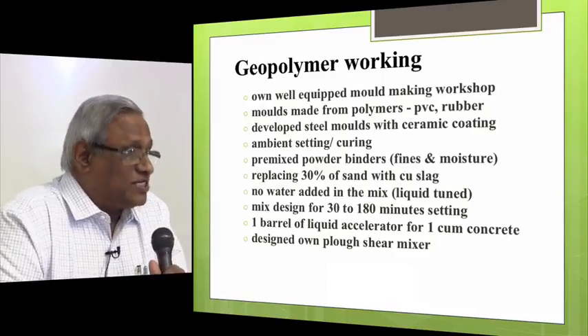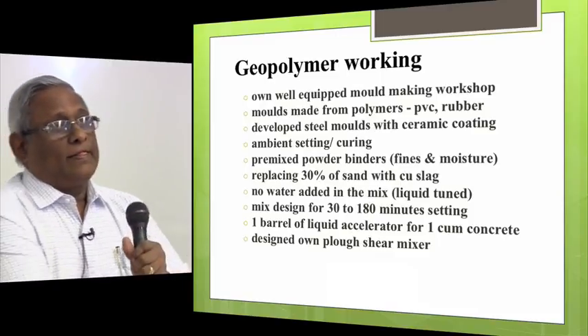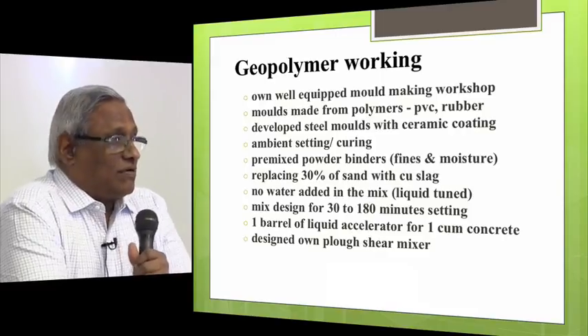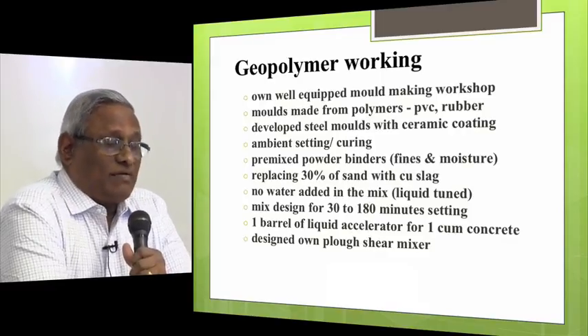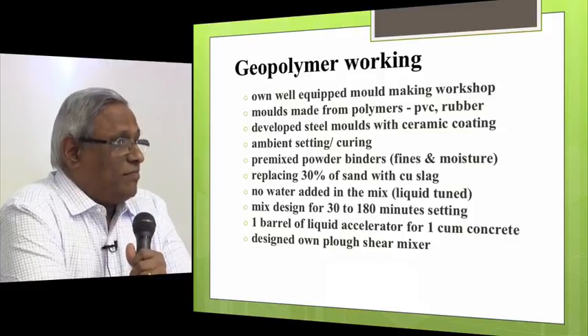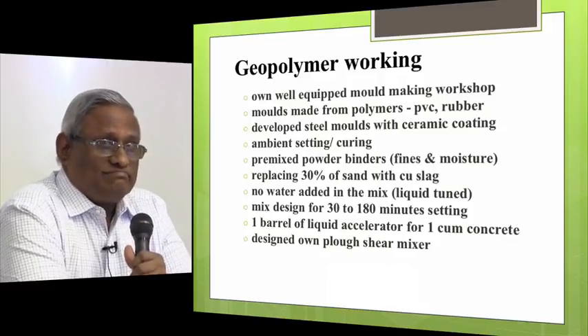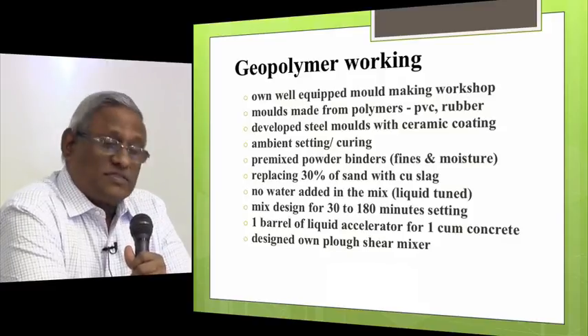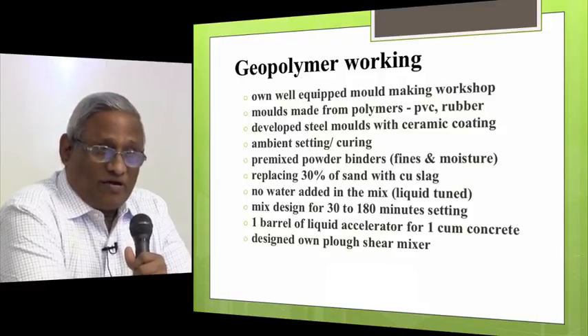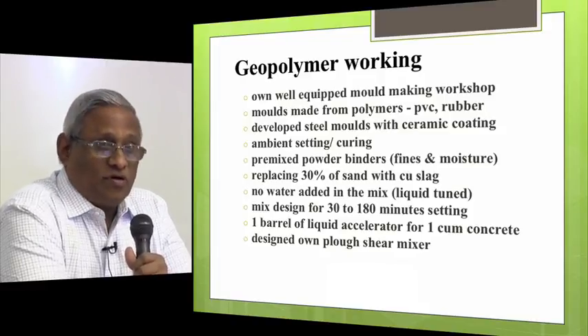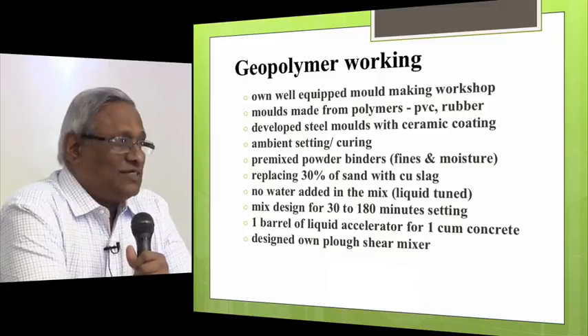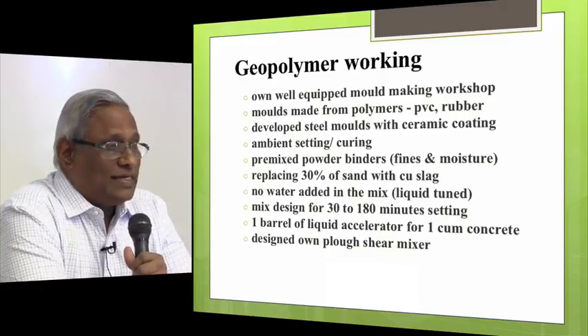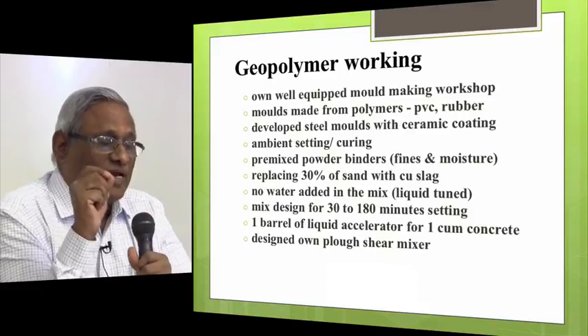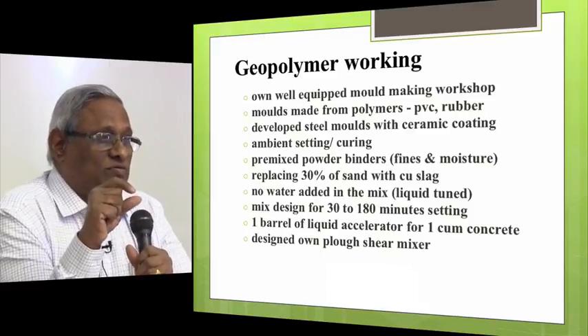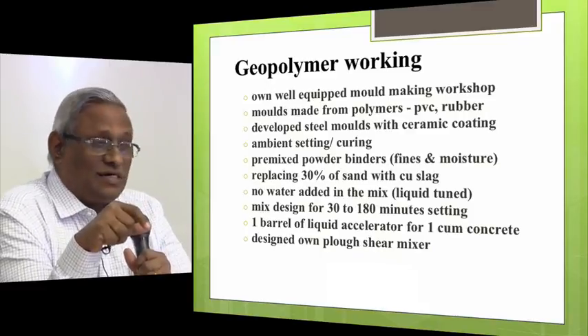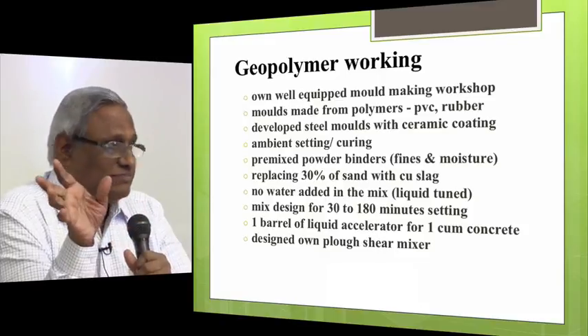And the very important aspect in our precast unit is the mixing of the concrete. The normal mixing of concrete in a pan mixer or in a barrel mixer or screw mixer, we are not getting proper results. So we spent a lot of time and we developed our own, we call it plow shear mixer. So it shears all the particles so that the activator is able to reach all the finer particles, and it's able to polymerize much faster.